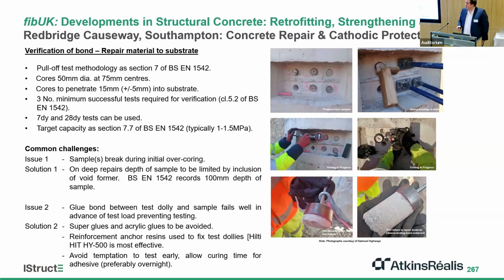So the final site issue we wanted to discuss was something we're seeing a lot of clients ask for on recent schemes, and that was the verification of the bond between the repair mortar and the substrate. Now, there is a test methodology in 1542, but it's predominantly lab-based. So what we've had to do is develop a system where that can be applied in the real world. So what we do is we've done 50mm diameter cores to replicate what's in 1542, and we're looking for 3 minimum successful tests from each batch. And what we've done in the top left-hand photo that you can see is done a line of 3 for 7-day strength and a line of 3 for 28-day strength.